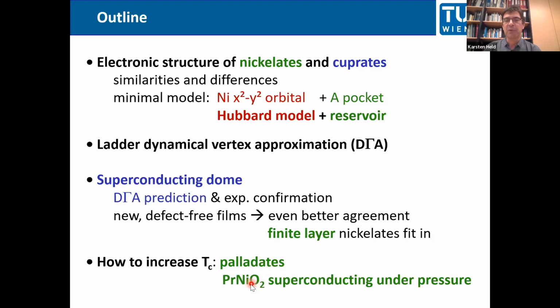There's some experiment by Wang et al. from Beijing for this infinite layer compound, but only up to 12 gigapascal. And what we see here is really very interesting, because even without any chemical doping, our prediction is that the parent compound will become a superconductor at experimentally accessible pressures.